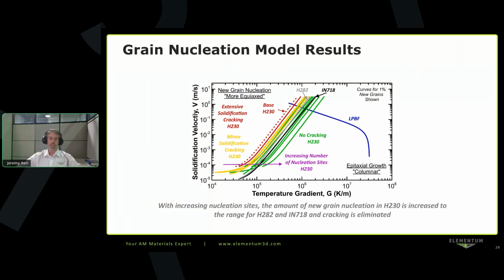So looking at the process with laser powder bed fusion in that blue line, you can see that on the right side, you're forming columnar solidification. On the left side, you're forming equiaxed solidification.